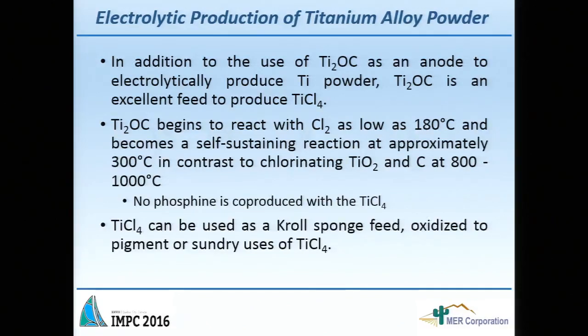Very important is, why do you have to chlorinate titanium oxide at such high temperature? One of the reasons is phosgene formation and also chlorinated hydrocarbon. When you use any source of carbon for reduction in presence of chlorine, if you're below 800 degrees, you're going to produce chlorinated hydrocarbon. Okay, no problem. And I worked on the Alcoa process for producing aluminum in the 80s. And the biggest problem that shut Alcoa was chlorinated hydrocarbon formation during the formation of aluminum chloride. Okay. And that's what shut the plant in Texas.